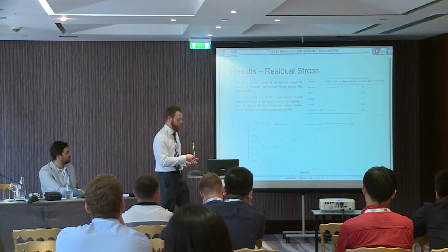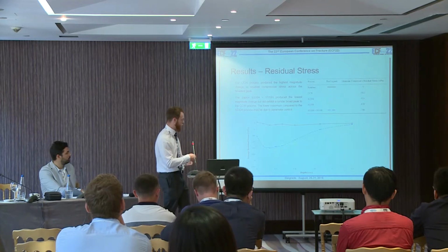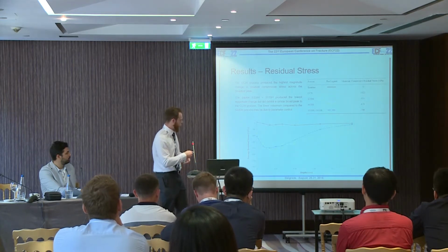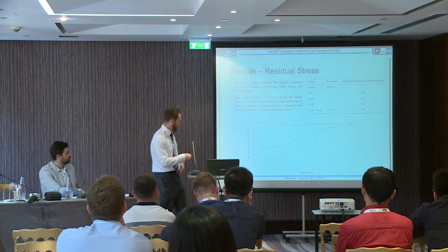The two standard single shot processes, so this is the S230H, this is the S330H. As we'd expect, the larger shot size gives us improved compressive residual stress deeper in the material. Perhaps the surprising one here is the duplex method.